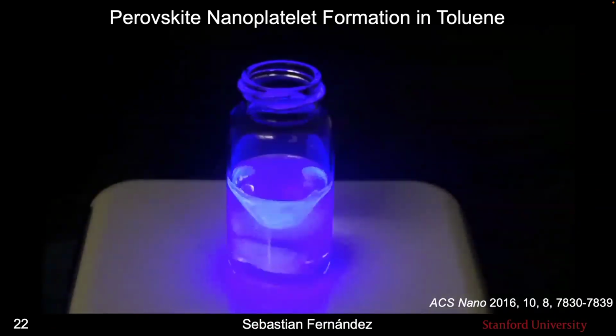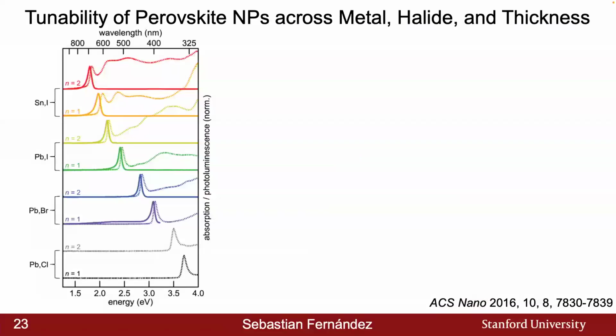And so now if we look at the optical properties of these materials, we can take these point by point of how they vary by metal, halide, and thickness. So the metals here are tin and lead. First focusing on this pair of absorption and photoluminescence spectra, and this one here, we can see that the tin-based systems are overall redshifted, or at lower energy, as compared to their lead counterparts. Across halide, if we compare the lead from iodide to bromide to chloride, as we move from iodide to bromide to chloride, we can see a general blue shift, or increase in the energy, of the photoluminescence and absorption spectra here.